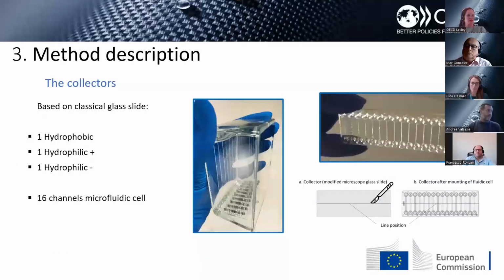Next, please. To develop our method, we prepared three different collectors, starting from a classical glass slide. We produced three different collectors: one hydrophobic, coated with a Teflon-like polymer; one hydrophilic positively charged; and one hydrophilic negatively charged, in order to test different materials with different surface charge, both positive and negative. All these collectors are mounted with a 16-channel microfluidic cell to allow injection of the sample into the channel. Next, please.